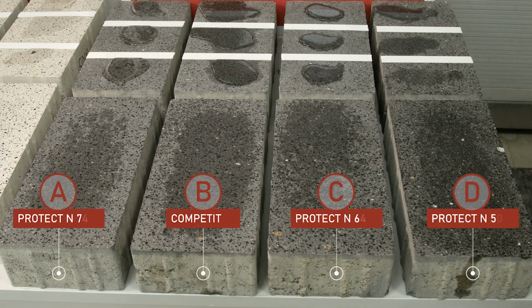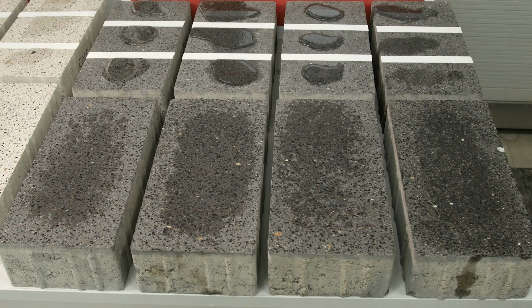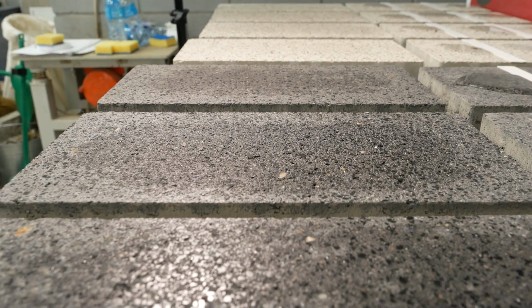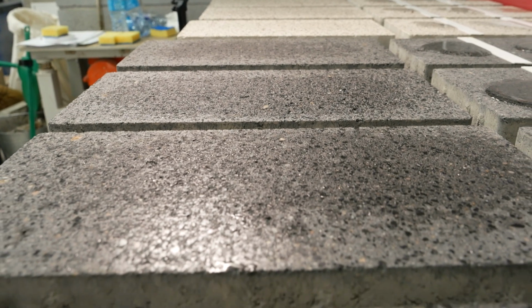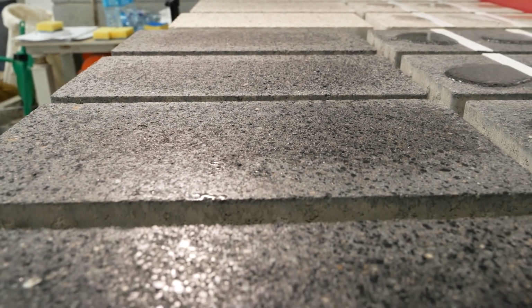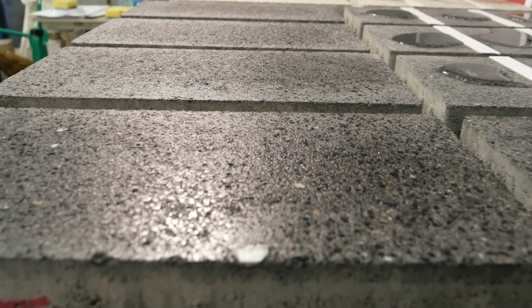Now let's look at all 4 samples of the polished concrete series at once. On sample 1, water practically didn't penetrate into the concrete and didn't form a water spot. Sample 2 shows the strongest water penetration and formation of the most intense wet spot. Similar pattern on sample 3. Sample 4 shows moderate water penetration and moderate water spot formation.